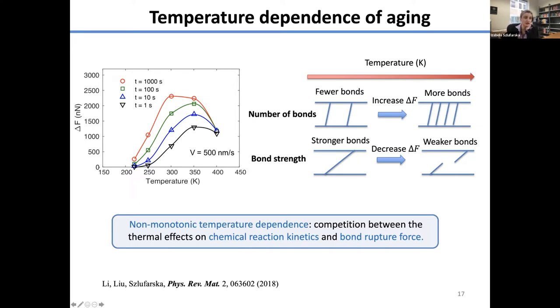So this is the frictional aging as a function of temperature for silica. Different curves represent different hold times, so you can just ignore the different curves. But you can see there's a maximum at about room temperature where the aging is maximized. So there's an optimum temperature. Why is that? Qualitatively speaking, we have a model for that, but the high-level picture is that temperature has two effects.